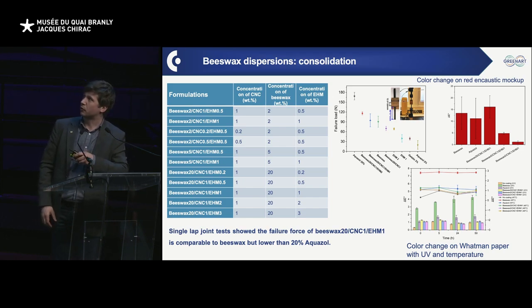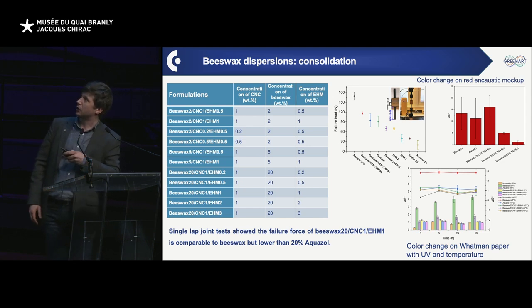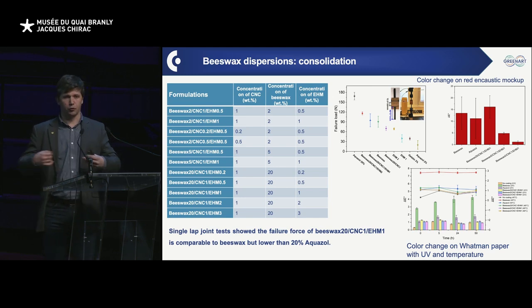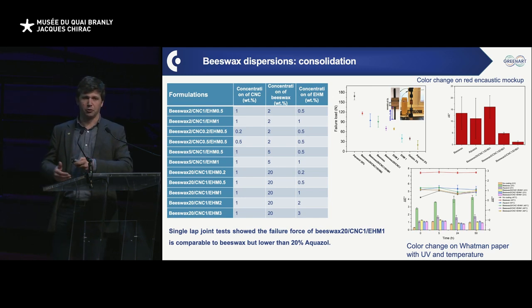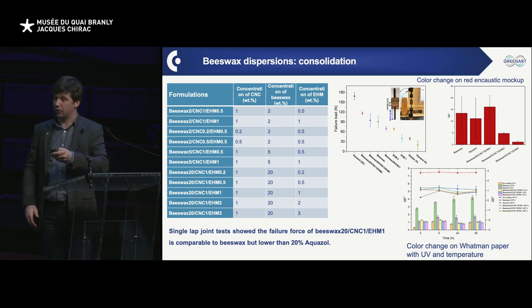Here you have the results from the tensile testing, the failure load at break, essentially. And we attach two pieces of wood. Well, here there are extensions to attach it on the clamp of the tensile tester. And then we measure how much force we need to break it. So the better the glue is, the higher the force is meant to be.